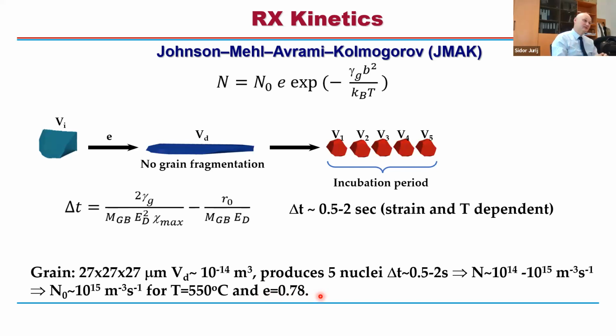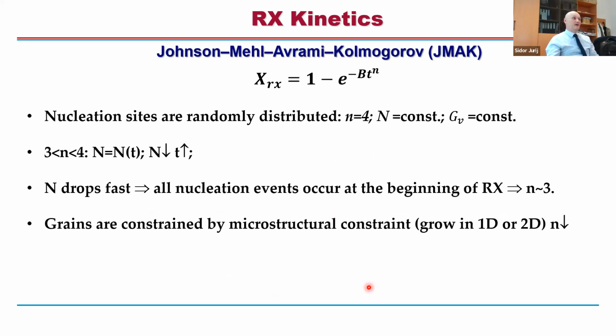E equals 0.78. In fact, we have checked literature sources which are claiming that one grain can produce 3-4 nuclei. So I based my assumption on this. Good. So at least we have the order of magnitude for N0. Then another parameter which we still do not know is the Avrami constant N. And this is the most difficult parameter to estimate because at least the rest you can calculate somehow. And this one, for the time being, there is no way.